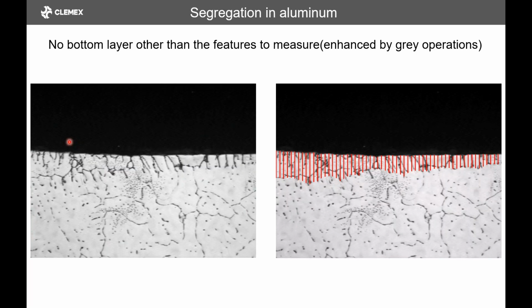Here, that's not really a coating, but it's still a layer that we need to measure. So this one is segregation in aluminum. Basically, when you let an aluminum casting, a big casting, cool off, what happens is that the chemistry kind of floats. Sometimes you might have some alloys that float more, and so you end up with a different structure